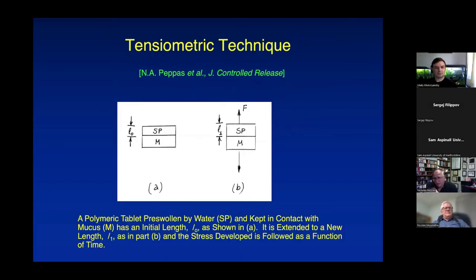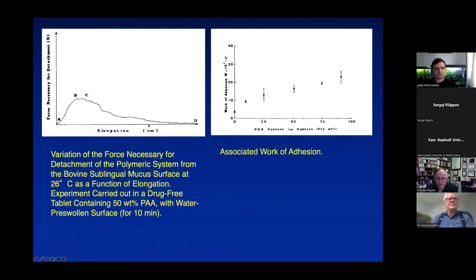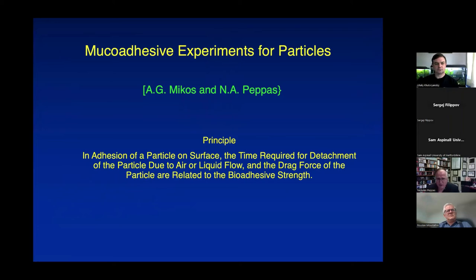And this was something we developed where we had a tensiometric device and we were able to measure the distance and the force. So if you look at it, you look at the force as a function of elongation. At some point, the system comes apart. This is the area under the peak. What is that area? Many of you will rush and say, that's the work of adhesion. It's not the work of adhesion. It's the work of fracture. But if adhesion and fracture are reversible, then it's equal to adhesion. Well, they're not reversible. But anyhow, many of us, including me, will take that area under here and call it the work of adhesion. And you can see something that you always knew, that as you increase the polyacrylic acid, the carbopol, it becomes a stronger and stronger system.